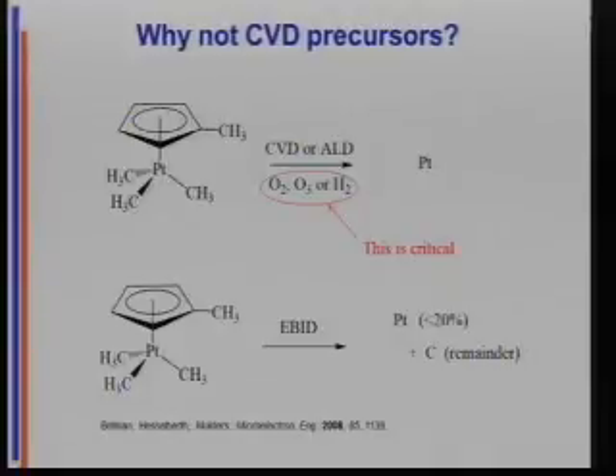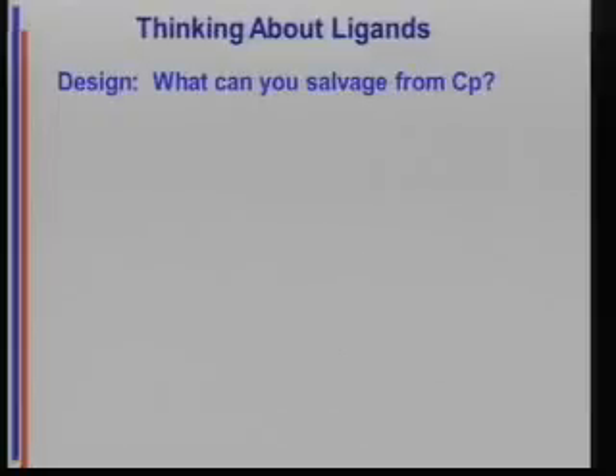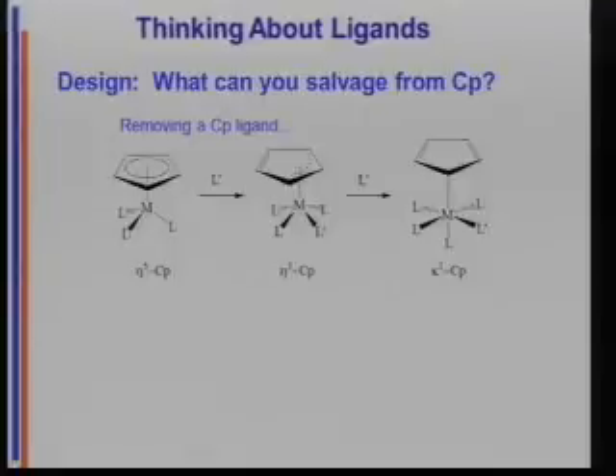All right, so maybe we should do better precursors. Okay, so I'm back to being an organometallic chemist. Can we salvage anything about those precursors? So if you're trying to get rid of a Cp, this is old work. This is Chuck Casey and Joe O'Connor, organometallic chemists. You get rid of Cp, one of the things you can do is add ligands, and you go to allyl, so you basically go eta 5, eta 3 to kappa 1.